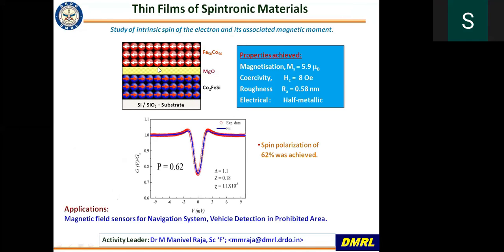This is one of the spintronic based thin films where we use tunnel junctions with an FeCo layer and MgO as a tunneling barrier, and Co2FeSi, which is the Heusler alloy. We have done the point contact Andreev reflection technique and measured the spin polarization. This is one of the most challenging techniques, as everyone knows, because we need a tunnel barrier of 1 nanometer and it has to be uniform throughout the film. So this is one of the most important challenges.